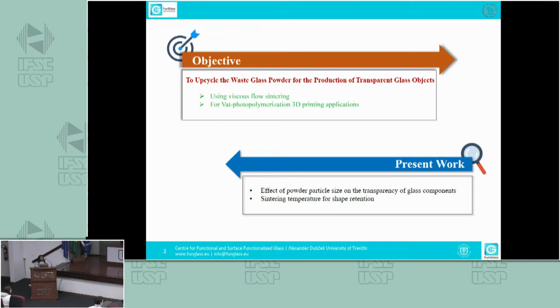I want to elaborate on my research project a little bit more. I am using waste glass powders to produce transparent glasses using the viscous flow sintering method, and I will apply the successful results to VAT photopolymerization 3D printing. Up till now, I have studied the effect of powder particle size on the transparency of glass parts. I have also studied the sintering temperature necessary for shape retention.